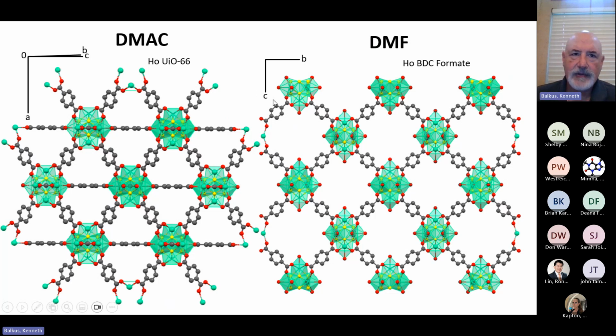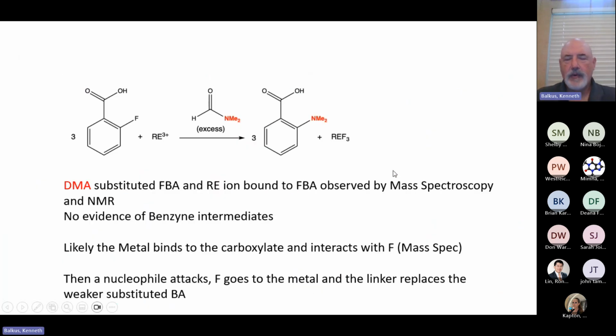Now, just to show you an example here too, when we do this reaction in DMAC, which is dimethylacetamide, which is what Juan first did. So this is the structure he first made. He got this UiO-66 structure, hexanuclear cluster, but when he did the reaction in DMF, he made this structure, which has formate, and you can't see the formate in this particular view. Apologize for that. It's going into the plane of the board, but they're now bridging formates into the structure. And of course, this formate comes from the DMF, and still the hexanuclear clusters. So we think that the DMA is important.